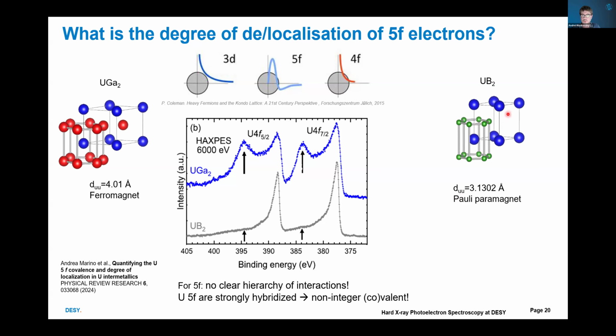And uranium boron 2 was expected to be itinerant, because it has a very small lattice parameter. And in the case of uranium gallium 2, we expected that the electrons are much more localized on uranium atoms because of the larger unit cell, and because of ferromagnetic ordering. And indeed, in the hard X-ray spectra, we saw a clear difference between the 4f states. In the case of UB2, the 4f states behave like metallic.